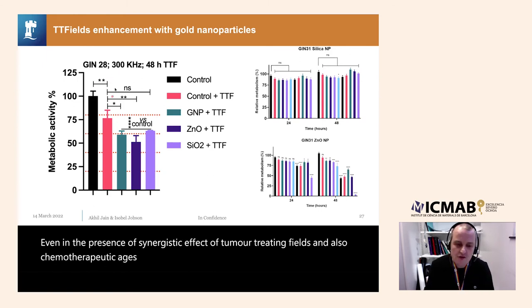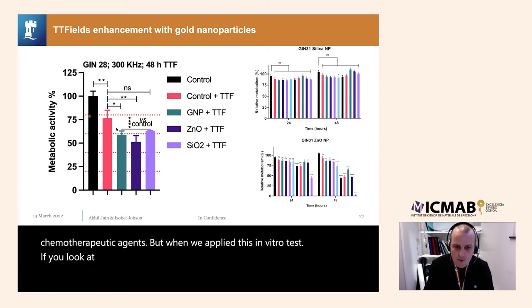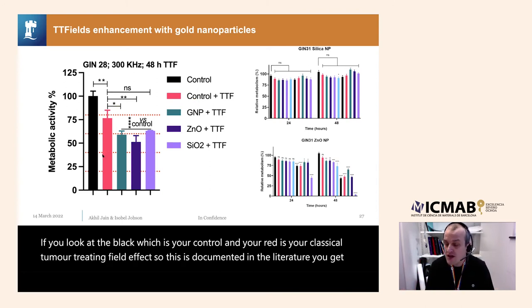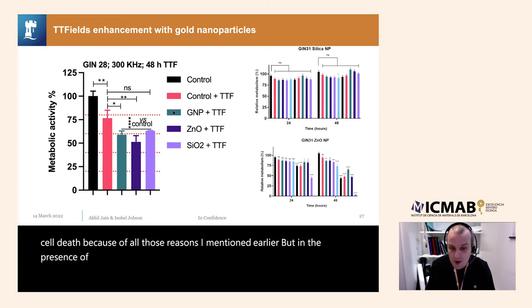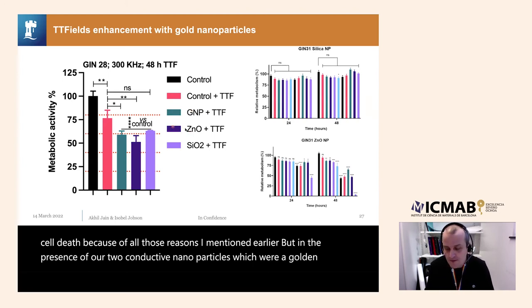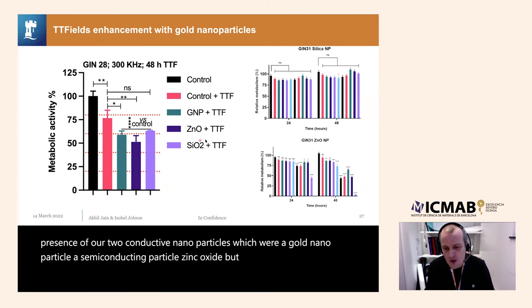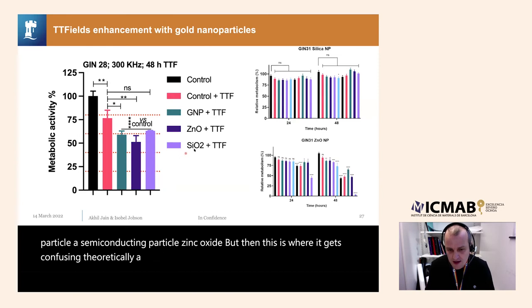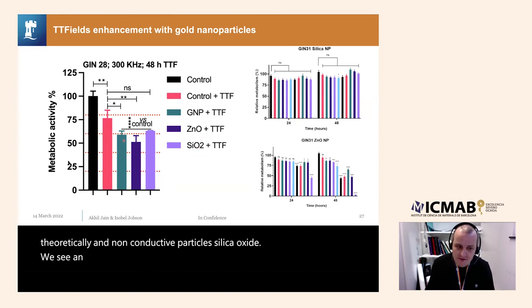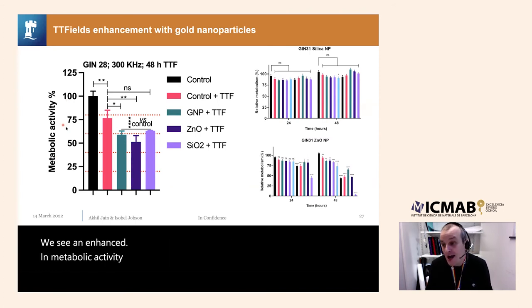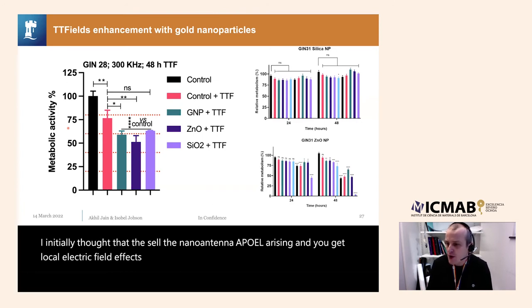But when we applied this in vitro test, if you look at the black, which is your control, and the red is your classical tumor treating field effect. So this is well documented in the literature. You get cell death because of all those reasons I mentioned earlier. But in the presence of our two conductive nanoparticles, which were a gold nanoparticle, a semiconducting particle, zinc oxide, but then this is where it gets confusing, theoretically a non-conductive particle, silica oxide, we see an enhanced reduction in metabolic activity, indicating, I initially thought, that the nano antennae are polarizing and you get local electric field effects interfering with cell processes causing cell death. There's a problem though. The SiO2 nanoparticle is a really high resistance particle and shouldn't polarize in the field.